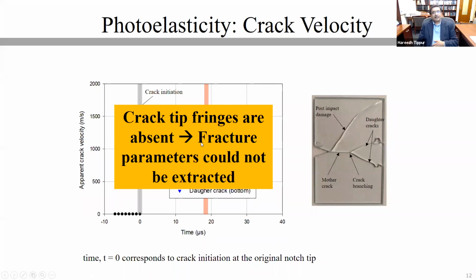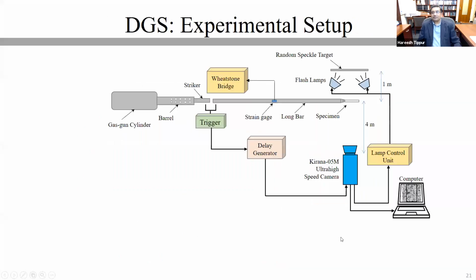The highlight that I'm making here is to emphasize the fact that the crack tip fringes are completely absent. You only saw the fringes near the compression zones, whereas there is no fringe at all in the tensile zone, in front of the growing crack. So as a result, the success of the photoelastic investigation was only partial because I don't have any information regarding the stress intensification that's happening in front of the crack itself. So we adapted different methods.